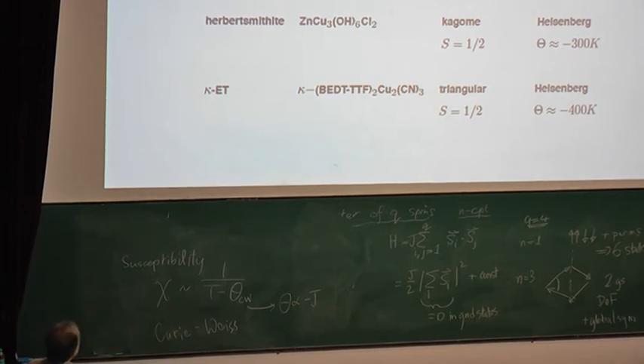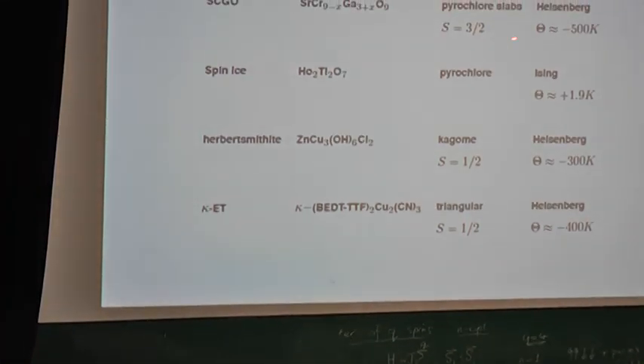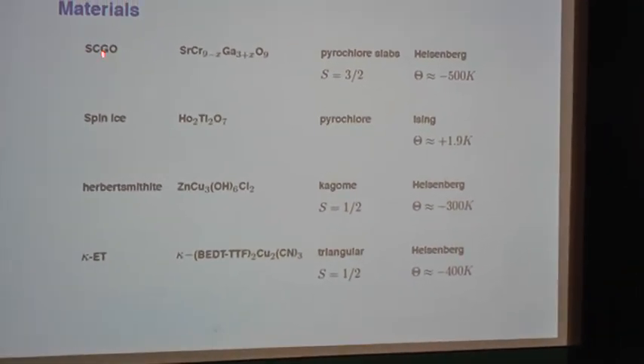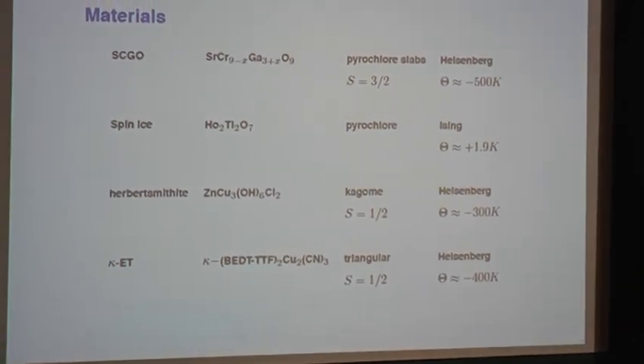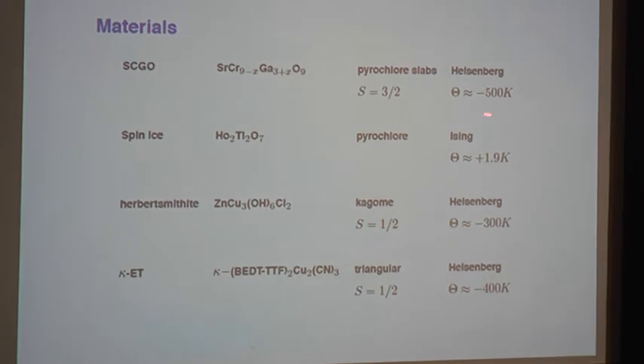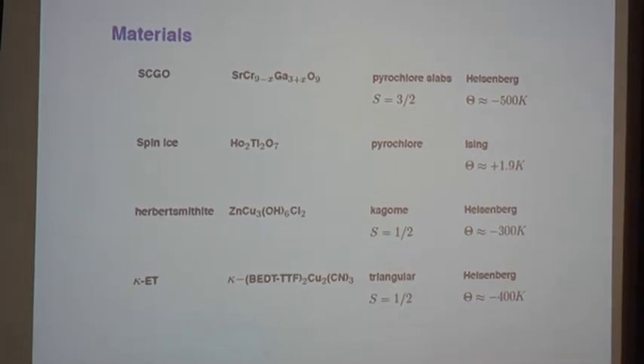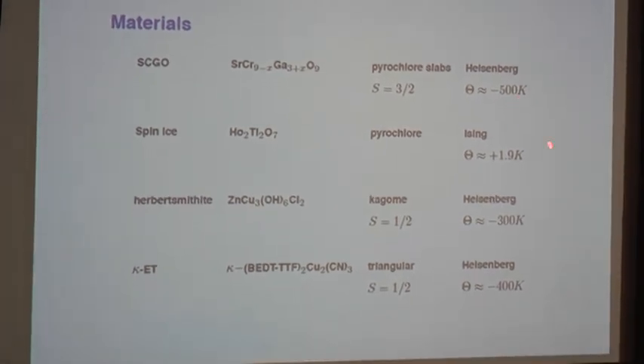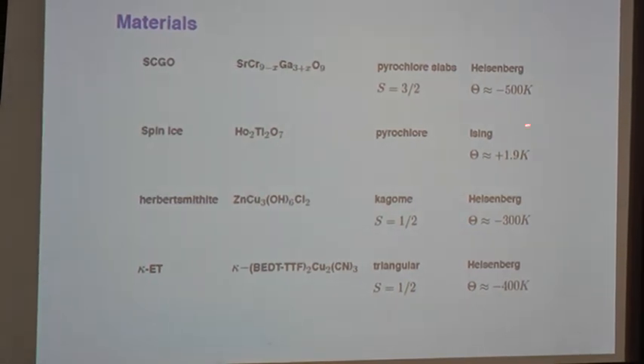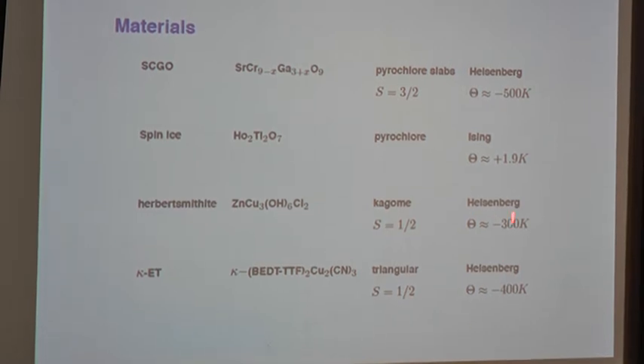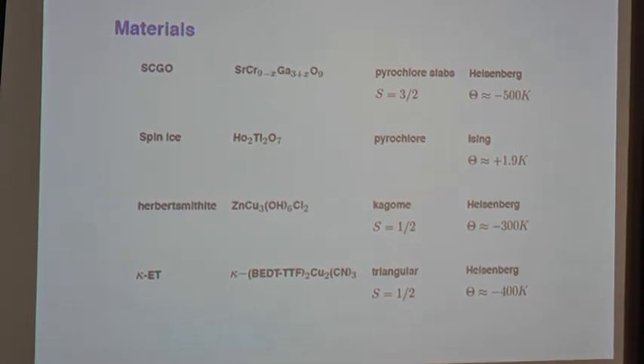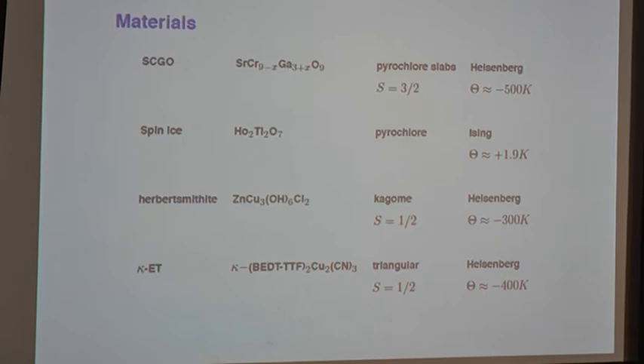And so you see that in this first material, SCGO, we have rather strong antiferromagnetic interactions with a Curie-Weiss constant of 500 Kelvin. We have much weaker ferromagnetic interactions in spin ice, and in these quantum materials we have rather strong antiferromagnetic interactions.